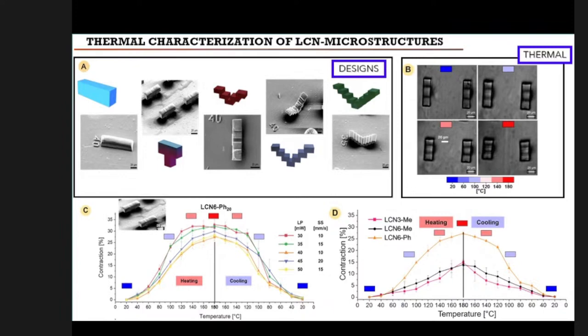But then I focused on understanding how changing the printing parameters, so the laser power and the scan speed, affects which kind of goal I can obtain. And I demonstrated that I can vary the actuation of the same material and the same microstructures only by changing the printing parameters. Then I made a comparison of the three different monomer mixtures that I used in these studies in order to understand which is the best material in terms of actuation, but not only, also for the morphology. And the LCN6, with the phenyl ring as substituent in the liquid crystal core, seems to be the best material in terms of actuation and morphology.